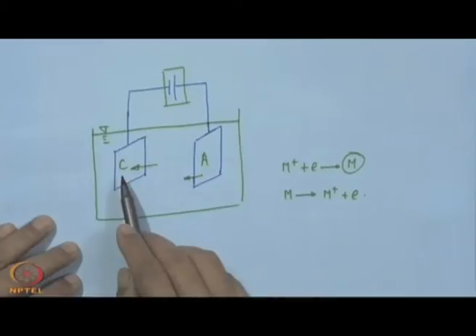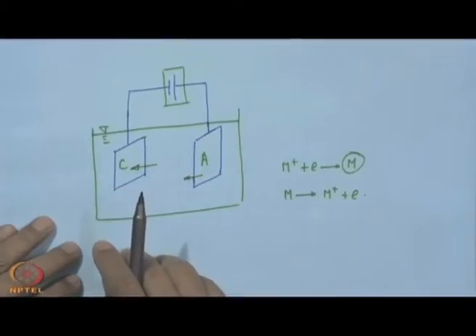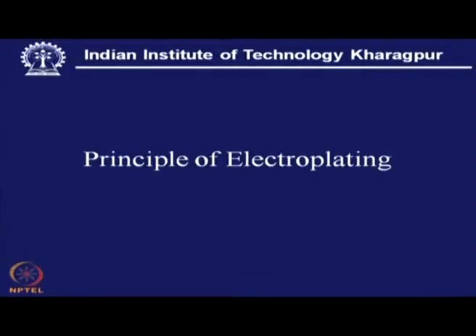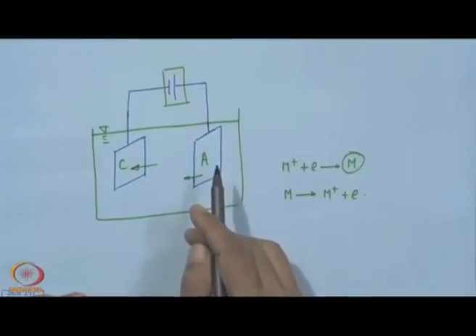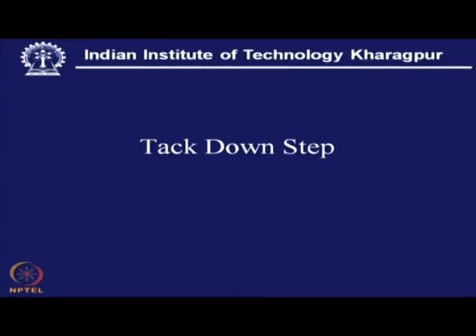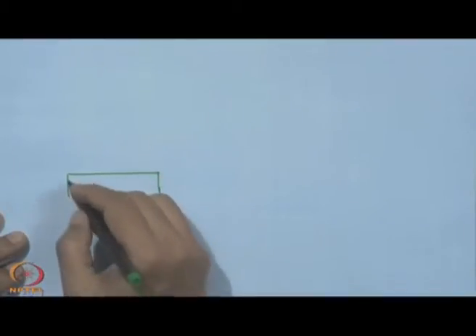Now, this is going to be used for realization of this electroplated abrasive tool, wherein the crystals are anchored over a metal or hard metal substrate by depositing this galvanic material around each crystal. So, there are actually two steps. The first step is called the tack down step, and this can be illustrated this way. If we consider one of the simplest cases, it is a flat surface which is placed horizontally. It can also be a vertical cylindrical surface.